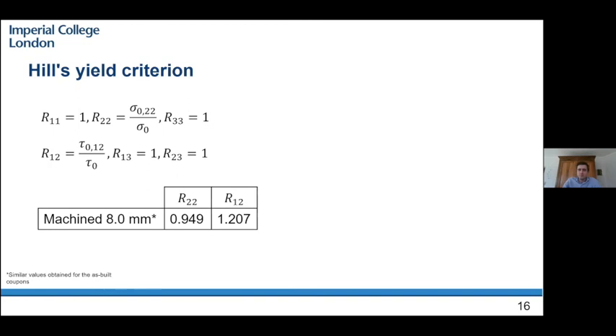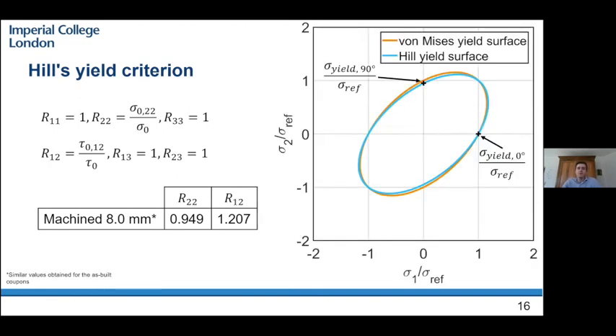machine coupons. Looking at how this changes our yield surfaces, in orange is the von Mises yield surface, and you can clearly see that the Hill's yield surface for the anisotropic material has been skewed. And this is due to the R factors that are introduced in the Hill's criterion.